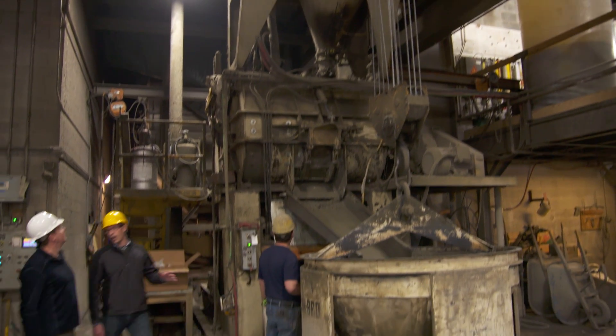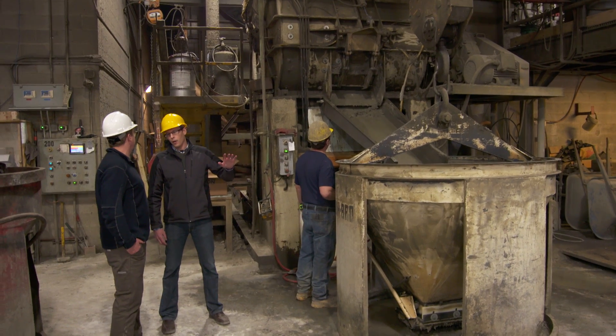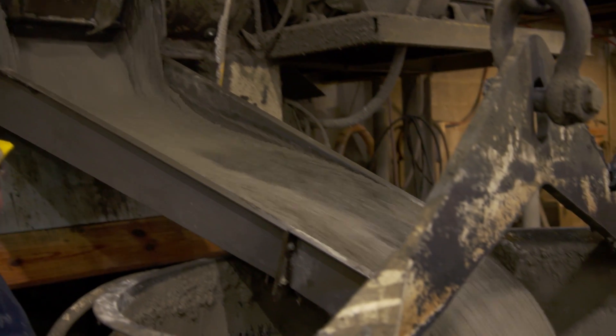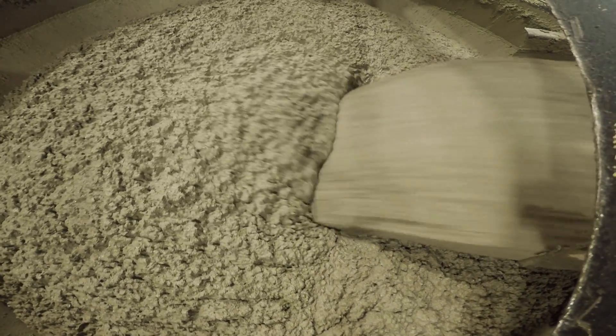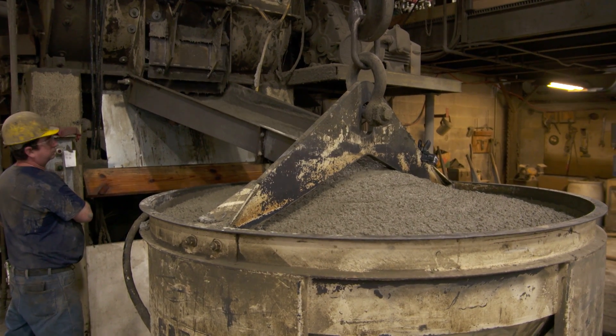This is where we're going to mix our concrete — a 5,000 PSI mix. We have 100% control over the mix because we're in a climate controlled environment. Typically on a job site you're going to see anywhere from 2,500 to 3,500 PSI. The reason for that is they can't control the conditions — you may have five or six trucks out there, sitting and waiting to pour, adding water and things like that. It just doesn't have the control.